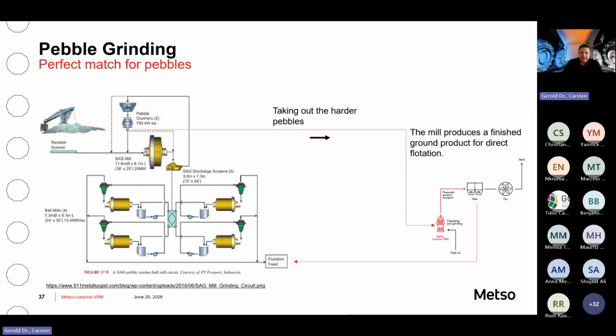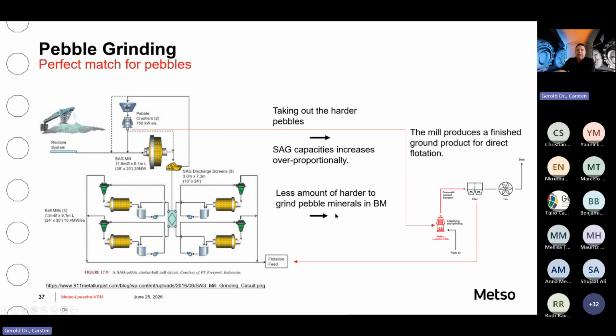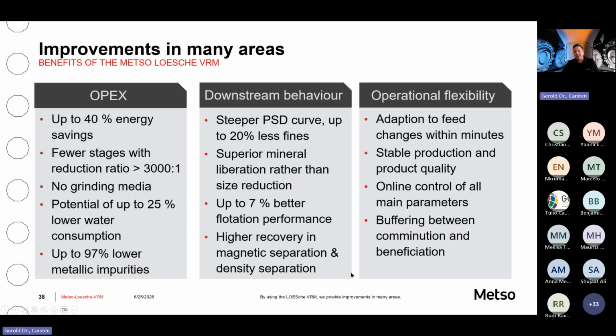And by taking out that harder-to-grind component from the complete circuit, your SAG capacities increase over-proportionally. At the same time, you feed less hard minerals to the ball mills, so the ball mills also benefit over-proportionally in capacity. So we think this is really a nice thing for VRM applications.